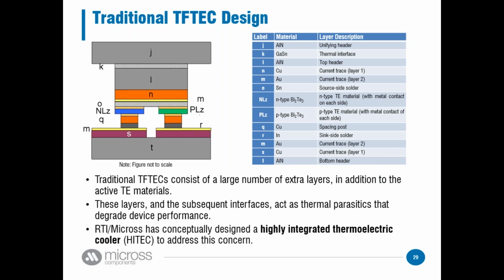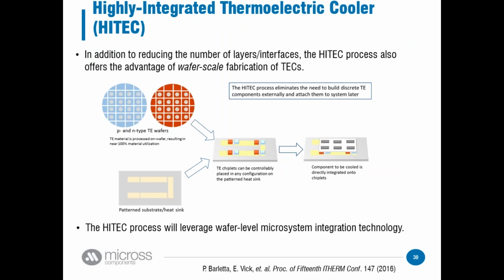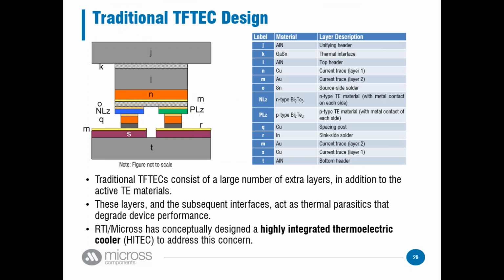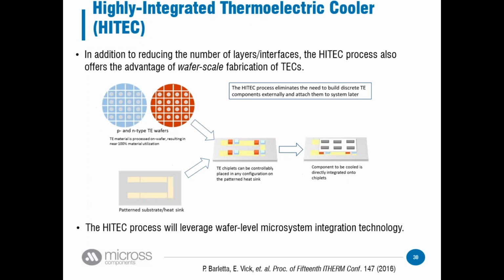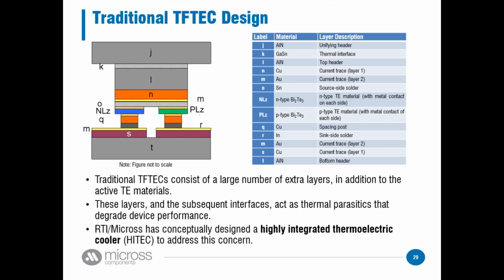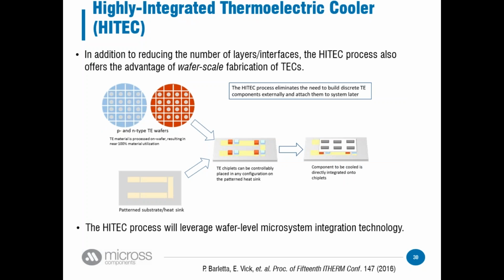But we have all this other nonsense. So the question is, is there a way to cut down on these layers and integrate these directly into the components that need to be cooled and directly into the heatsink? So that's what we have here. If we grow our thermoelectric material directly on wafer, process them on wafer, and then, instead of putting them on a separate header that will then be thermally attached to the heatsink, let's integrate the devices onto the heatsink themselves right here, and actually integrate the part that's being cooled. Let's integrate that directly onto the thermoelectrics as well, so you don't have all these structural headers to hold everything together. Let the heatsink and the device you're cooling hold everything together. So this is a tricky integration problem, but something we're working on now.